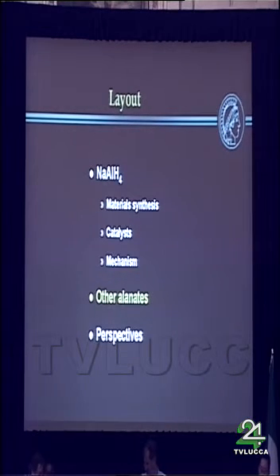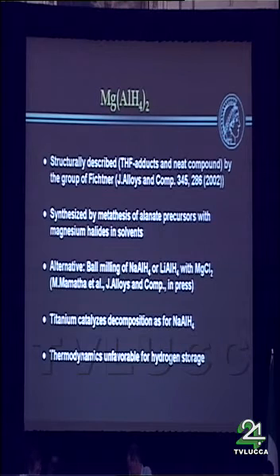I want to move to other alanates, briefly touch what we have there. Magnesium alanate is, I would say, except for lithium alanate, the second well-known system. It was structurally described by the group of Maximilian Fichtner. In this paper, which is cited, the THF adducts and ether adducts were structurally described. In a subsequent Inorganic Chemistry publication, also the neat compound was described, synthesized by a metathesis reaction. We have found an alternative method which is our standard tool for making other alanates, which is ball milling of sodium alanate or lithium alanate with magnesium chloride or other halides, and then you make, again by a sort of metathesis reaction, the other alanates.